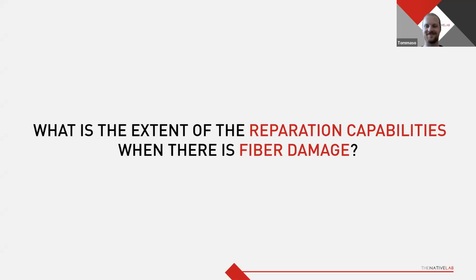Perfect. And Amaël, in the video we saw interlaminar cracks, maybe just for the figure, but is your system equally effective for intralaminar cracking? Again, it depends on the thickness of the crack. To some extent, yes, it works well. But if it's passing a certain threshold of thickness, then it's going to be more complicated. And with an intralaminar crack, you start to have also some fiber damage. Yeah, usually it's a combination.